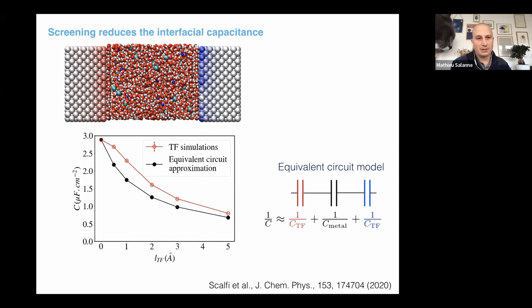Then the important quantity when you simulate this kind of system is the interfacial capacitance, because this tells you the response of your metal to a change of potential. And in fact, it's a quantity that you need to optimize in a supercapacitor. And you can see that something that is expected, of course, is that the more you screen your metal, the lower the capacitance is. But what is interesting to see is that in previous work, the hypothesis was that there were three different capacitances: two that were called quantum capacitance and were only due to the screening inside the metal, and the third one was the interfacial capacitance due to the liquid.